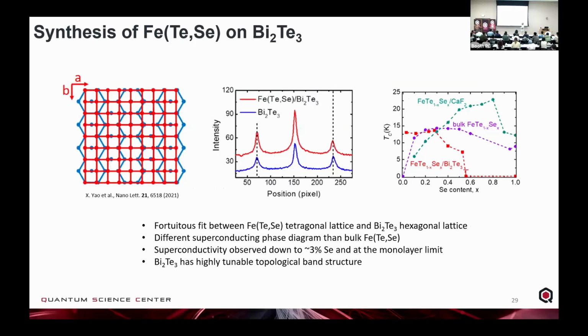that we're looking for. And so one of the things that we're doing at the Quantum Science Center is asking how we can sidestep this. We want systems that have the topology, we want systems with enhanced Tc, but we want to be able to minimize the inhomogeneities from this doping. And so here, we're lucky enough that we can look at this iron selenium tellurium, but if you grow it on bismuth telluride, which is a topological insulator, you can maintain a very high transition temperature, but with less and less doping.